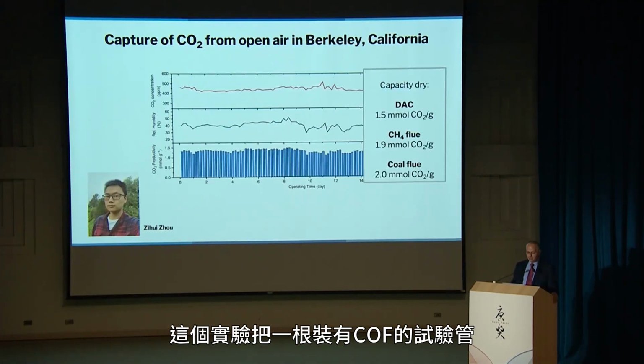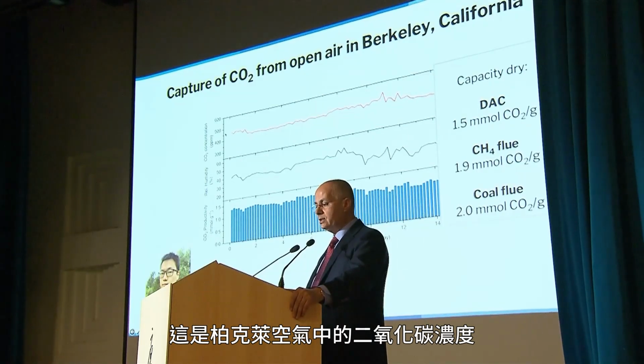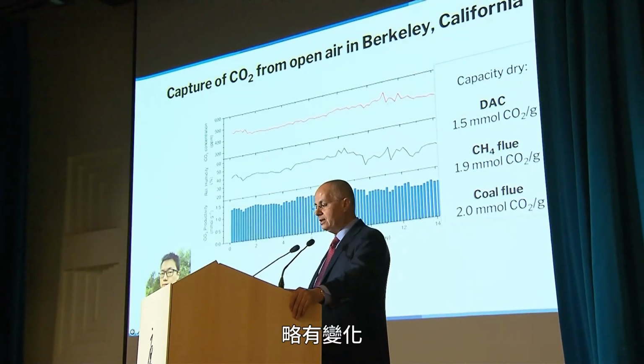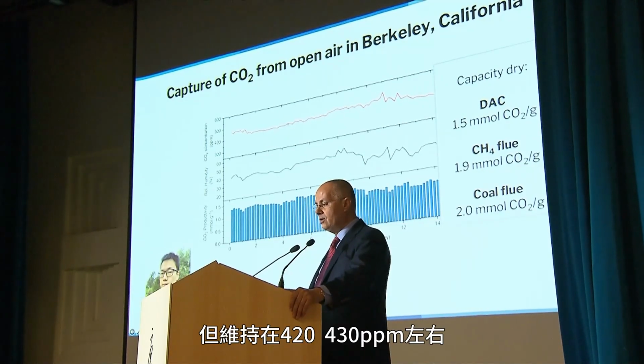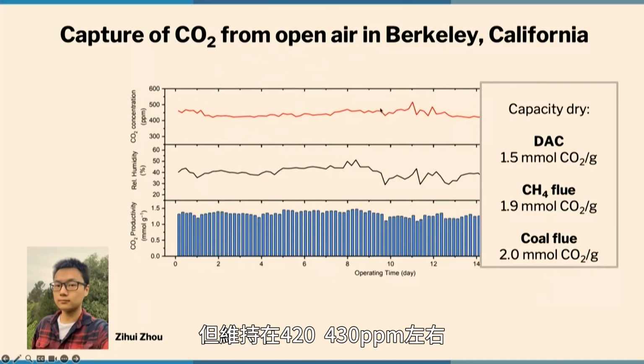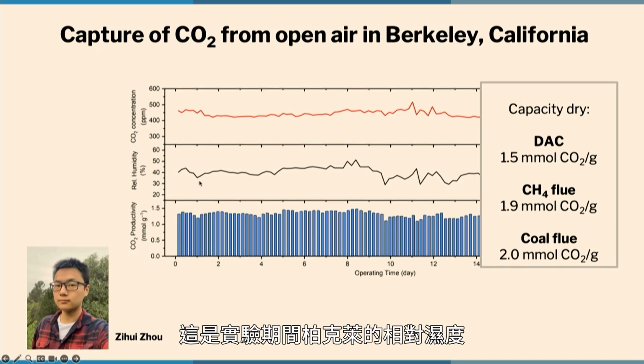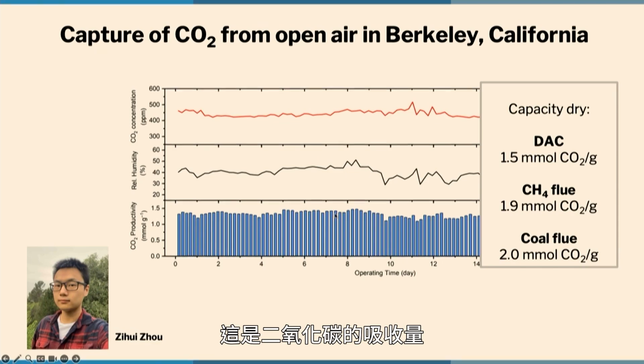Okay, this experiment takes a tube of this COF, which is a powder, and exposes this to air in Berkeley, where I work. Here's the CO2 concentration in Berkeley air. It varies slightly, but it hovers around 420, 430 ppm. This is the relative humidity in Berkeley during the days of the experiment. And this is the CO2 uptake.